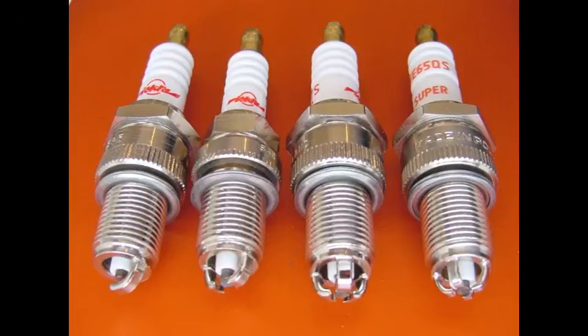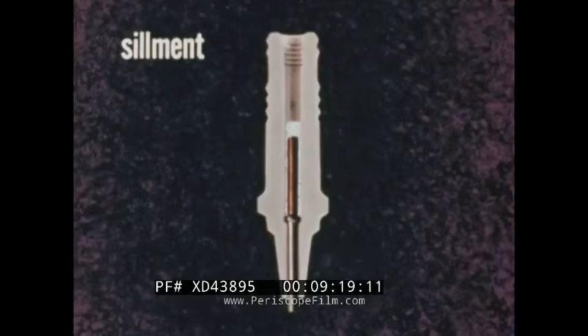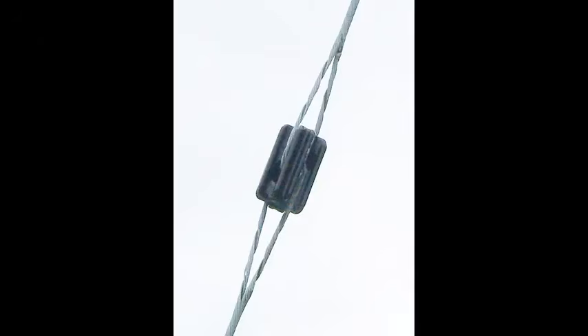The central hole created another problem. The electrode had to be sealed into the insulator without cracking it or allowing combustion gases to leak upward. A Champion patent filed in February 1942 described pre-firing the ceramic until most shrinkage had occurred, inserting the electrode, and then using a rapid final firing to shrink the remaining bore into tight contact. Other designs used glass seals, conductive glass mixtures, cements, and carefully matched metals. Every interface mattered because ceramic and metal expand at different rates. Heat a badly designed assembly, and the metal may pull away, crush the ceramic, or place it under tension.